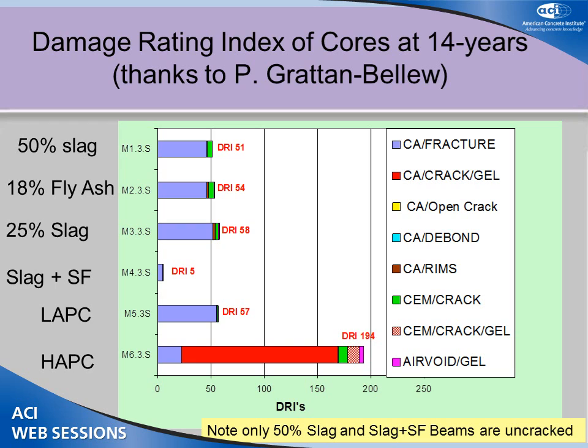Typically, if your damage rating is around 50 or less, you assume it's not damaged. But again, this is at 14 years. At 20 years, we haven't taken cores. It's one of the next objectives to get another set of cores to see if these numbers have risen. Of course, the high-alkali cement one that had cracked soonest had the big number, up around 200 by that technique.